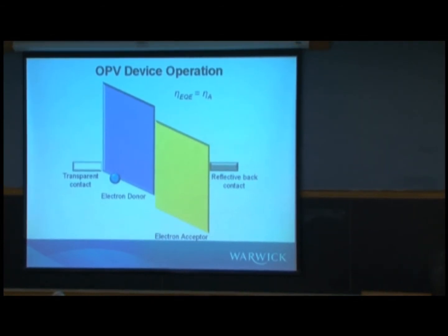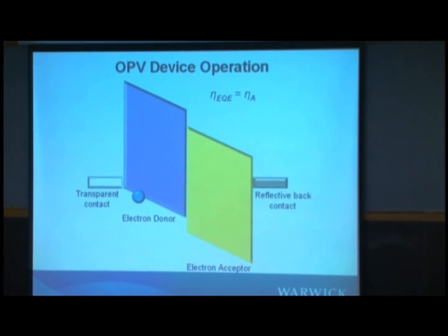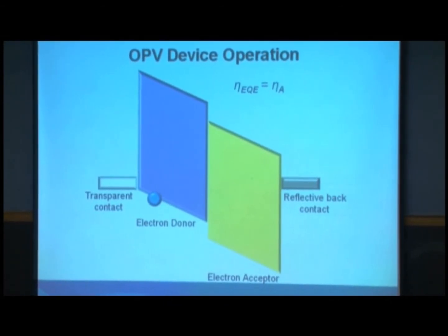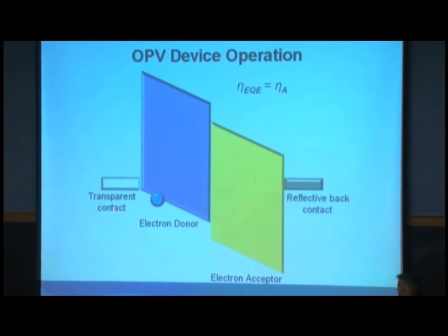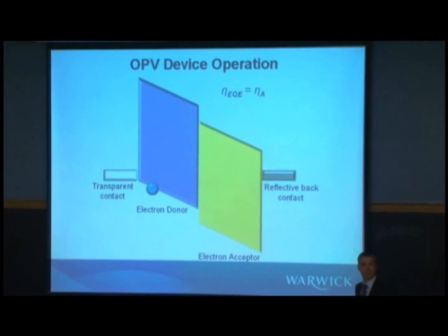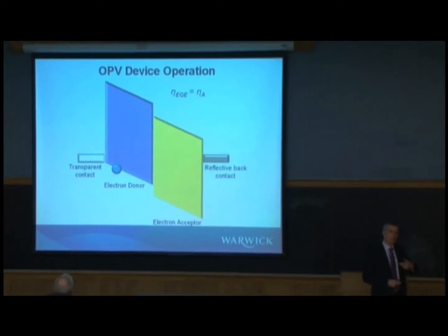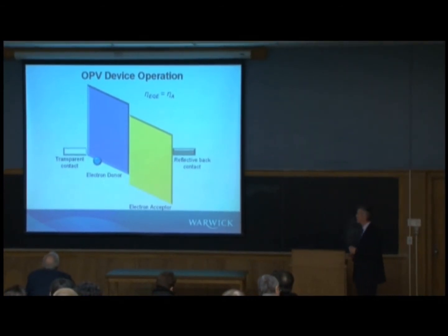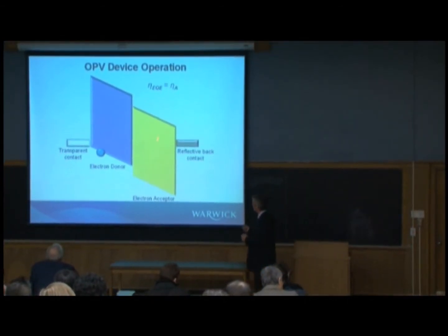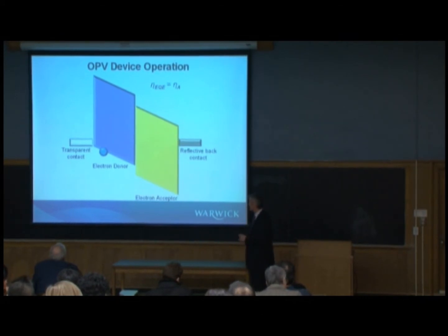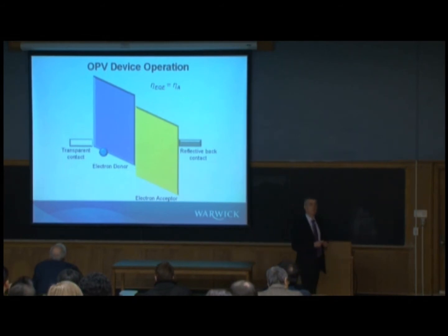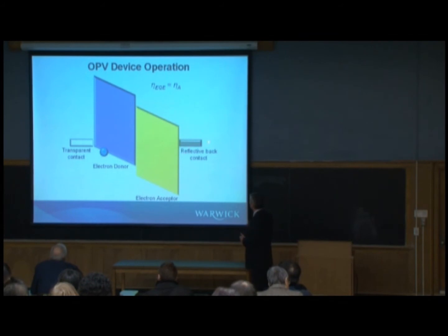So a little cartoon about how an organic solar cell works. This is the simplest type of organic solar cell. We have two electrodes, one transparent, so the sunlight's going to come in through here. That's typically indium tin oxide, but it could be another transparent conducting electrode. We then have two organic materials. Remember I said a donor and an acceptor. We have an electron donor material here in purple, an electron acceptor material here in yellow. Both of these are organic materials typically. And then you'd have a reflective metallic contact, typically aluminium. Again, you could use other metal electrodes.